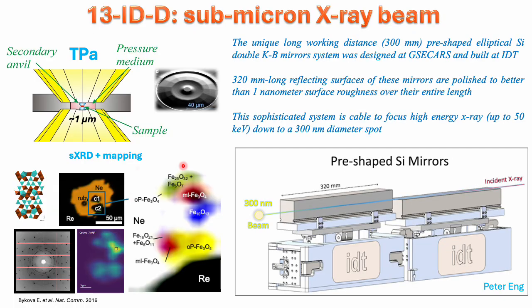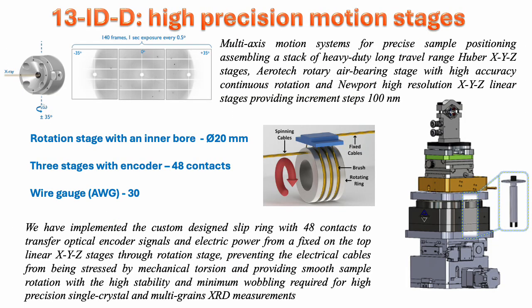We decided to upgrade our focusing system, replacing our old KB system with a unique pre-shaped elliptical silicon double KB mirror system. That should allow us to focus the beam down to 300 nanometers. To handle such a small beam, especially when collecting single crystal diffraction data where we need to rotate a sample up to 70 degrees with high precision, the sample should stay on the rotation center with sub-100 nanometer precision.